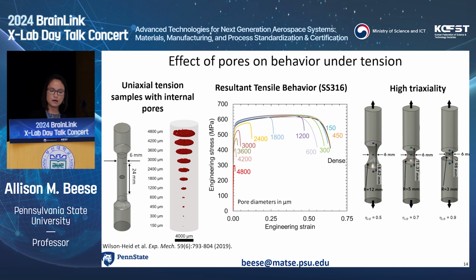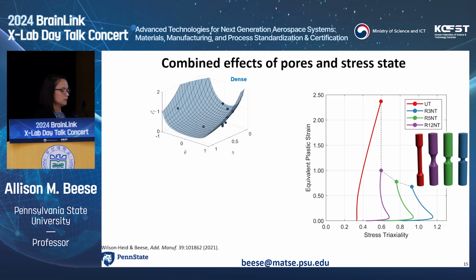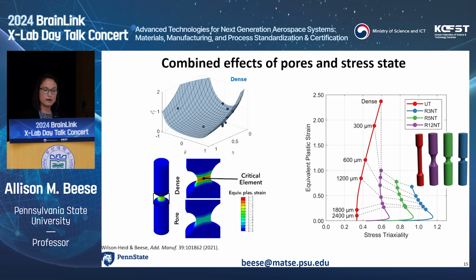So if I want to place this in context with what we just spoke about, we have our 3D fracture locus, strain to failure as a function of those two parameters. And what we're looking at here for these round specimens is just this right-hand side, so load angle parameter of 1. So that's just pulled out here. We have our ductility versus stress triaxiality: increased stress triaxiality, lower ductility. If we now look at adding pores in, we can see that as we add pores, our fracture strains start to drop. And then also the dependence on stress triaxiality drops as well.